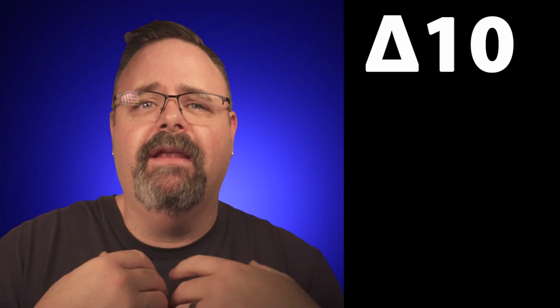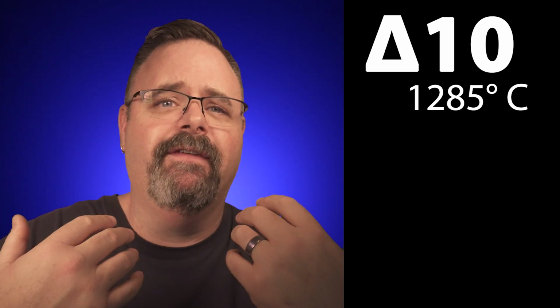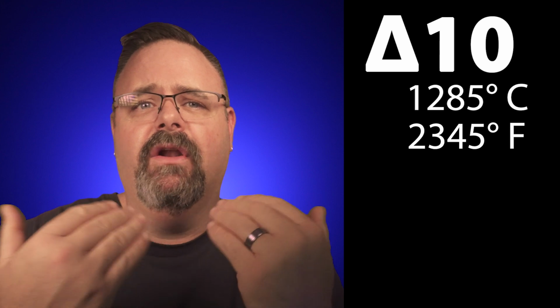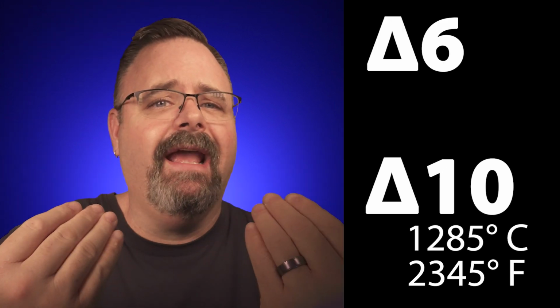We're just building up heat till we get to the end of the firing, which is when the melting takes place. And this is a huge deal because although it seems like cone 10 and cone 6 are really similar temperatures, they're actually quite far apart during that actual melting part. Cone 10 firing is going to be 1285 C, and that is considered high temperature. Well, cone 6 is 1222 C, and that difference is massive.